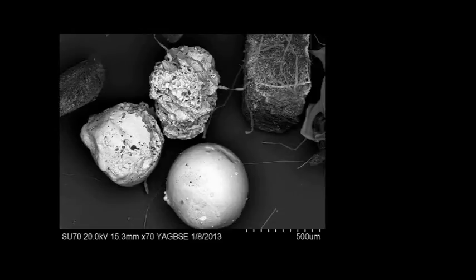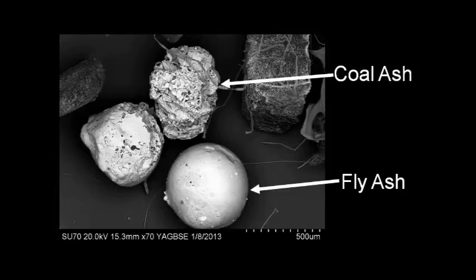So basically we ended up finding that 8 of our 21 samples contain some amount of ash, coal ash or fly ash. Coal ash comes from essentially the inorganic remnants of burning coal, so it's often referred to as bottom ash. This is the stuff that just can't burn and is very inorganic in nature. Fly ash is formed from the condensation of gases that are being emitted out of the smokestack, and because it's formed from a condensation, you'll notice how beautifully spherical in nature these particles are.